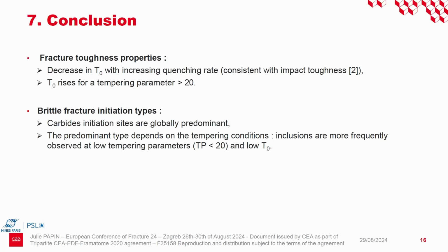So to conclude and to summarize the presentation on fracture toughness properties, we can note that there is a decrease in T0 with increasing quenching rate, which was consistent with impact toughness. And also there is a rise of T0 for tempering parameter over 20. And about the brittle fracture initiation types, we can note that globally carbide initiation types are predominant, but these depend on the tempering condition. Inclusions are more frequently observed at low tempering parameters and low T0, while carbides are more often observed at higher T0. Thank you for listening.